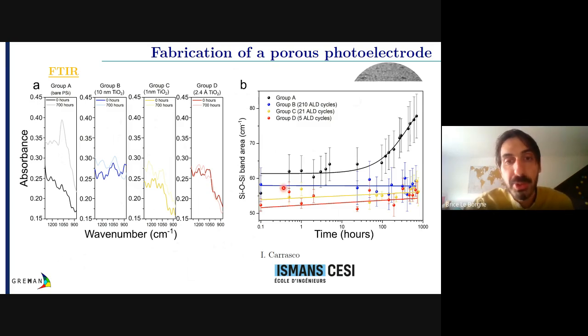So to plot it differently, that's exactly the same results, but after 0 hours, so the first measurement, and after 29 days, so you can see a bit better. And you can see on the bare silicon, you have this peak appearing. And here we plotted the actual area below these curves. And you can see that only for bare porous silicon, you see an evolution of this area.